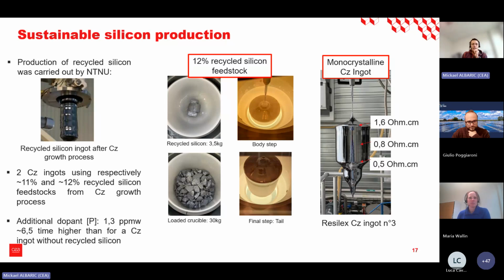I would say we will see during the next evaluation how the residual boron concentration in the ingot has an impact on the evolution of the cell efficiency, and if it's problematic for the lifetime of the final cells. If we have solutions to mitigate the presence of boron, I would say we can maybe increase to 15%. It's not a problem. Otherwise, we will need to find additional thermal treatment or processes in order to mitigate the presence of boron inside.